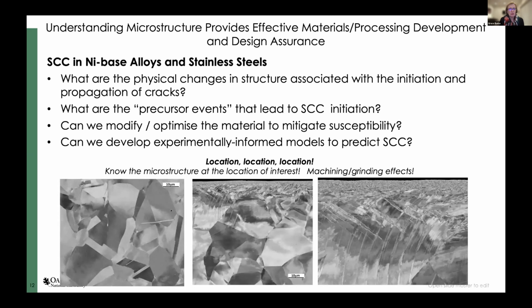A lot of work, stress corrosion cracking has been around for well over 100 years, in different materials. And characterizing the material is really important. I know I probably sound like one of those real estate programs, but what is really critical is location, location, location. I've got some images here. These are just backscattered electron images, but this is an austenitic stainless steel with a nice microstructure. We could study this from our components, study this microstructure and try to figure out why it is susceptible to SCC.